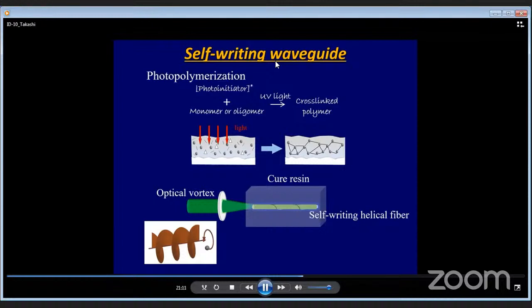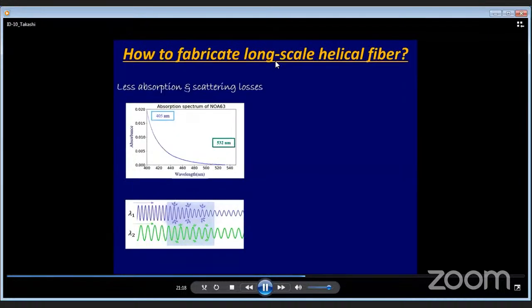This is 2-1. We perform the experiment. At that moment, how to fabricate long-scale helical fiber? The wavelength of the light source is quite important. We prepare this material, NOA63. This is the absorption band of the NOA63. UV light or visible light, which is better?